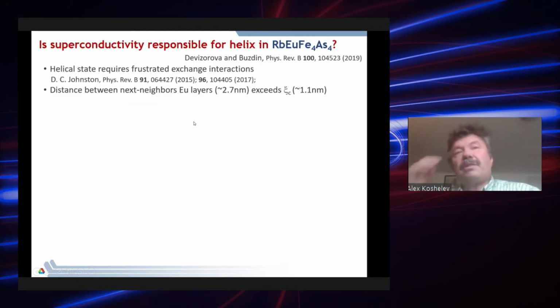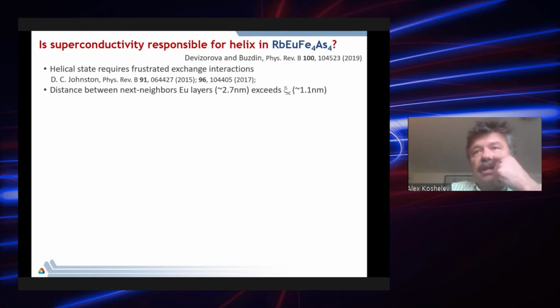So, the main question is: is superconductivity responsible for such a helix? This was actually proposed in this paper. And I see, in my opinion, that it's almost inevitable that superconductivity plays a role. There is a very simple argument. Helical state requires frustrated exchange interaction. It means that it's not sufficient to have only next-neighbor interaction, next-layer interaction. And the distance to the next neighbor, the second neighbor, already exceeds the coherence length in this direction. This means that superconductivity strongly influences this interaction. It must play a role.